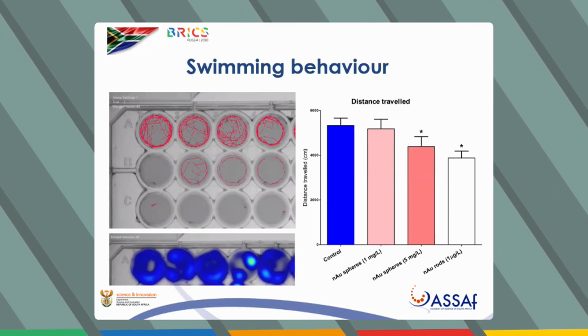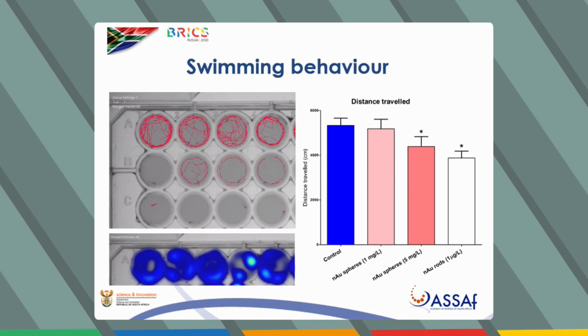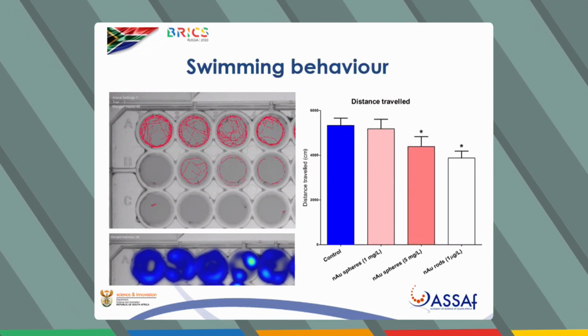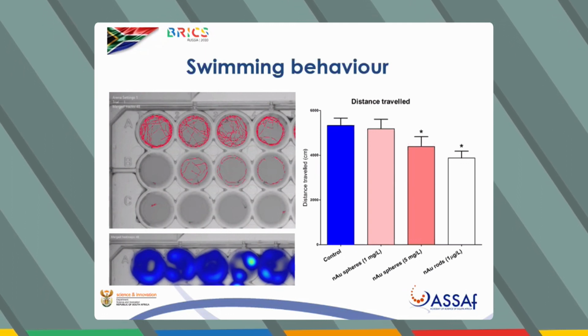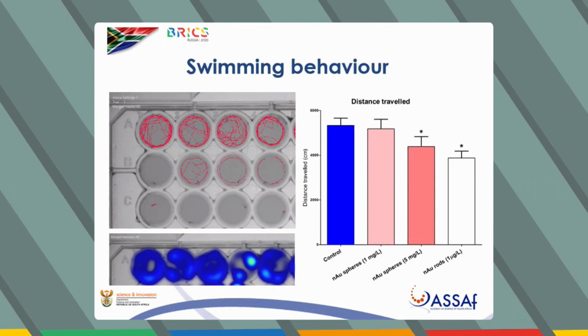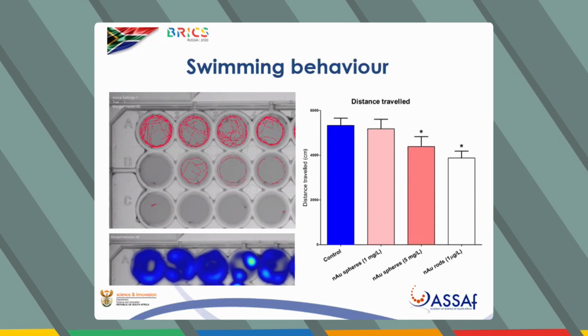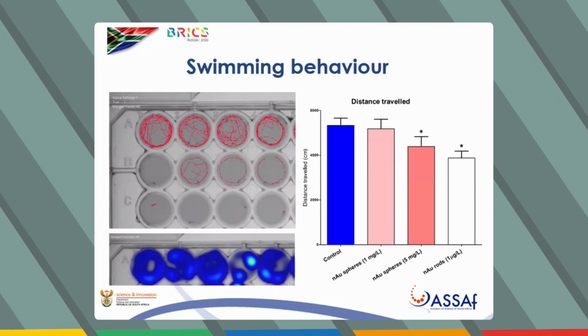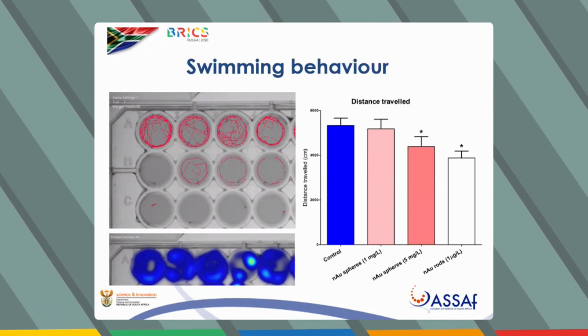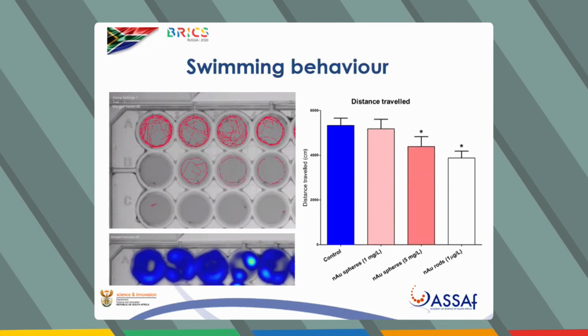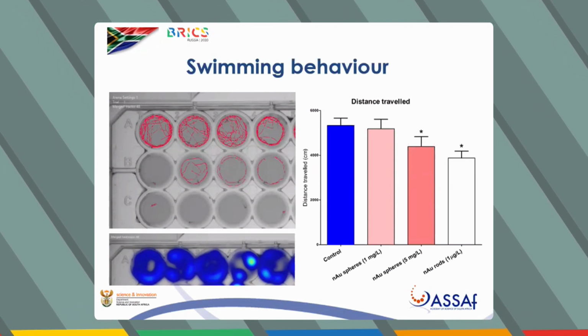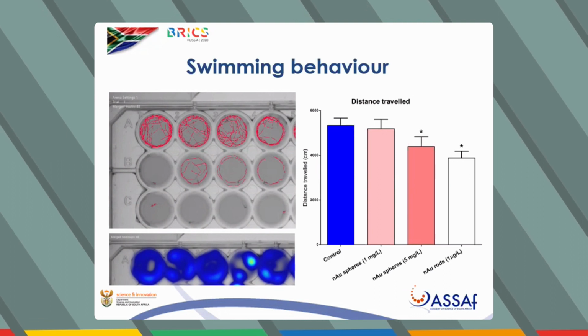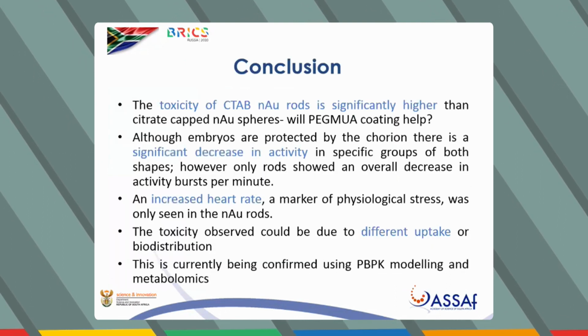With the swimming behavior, although at the low concentrations we don't see toxicity, we do see decreases in the swimming distance of the fish at a 5 milligram per liter concentration, and as low as 1 microgram per liter in the rods group. So this indicates, as we've mentioned, that the fish are either not moving because of a mechanical reason, as it could be on the eye, or it could be physiological, where these particles accumulate in the muscle tissue of the fish. This would then further affect their ability of predation, so predators eating them, their feeding behavior, as well as their social behavior. As I've mentioned, these fish are highly social species.